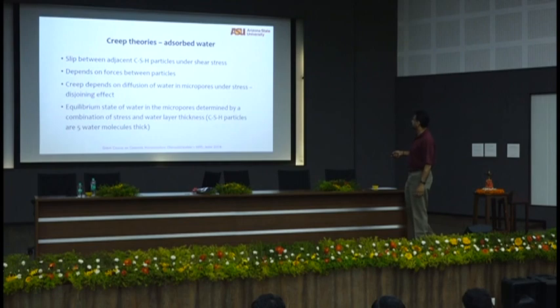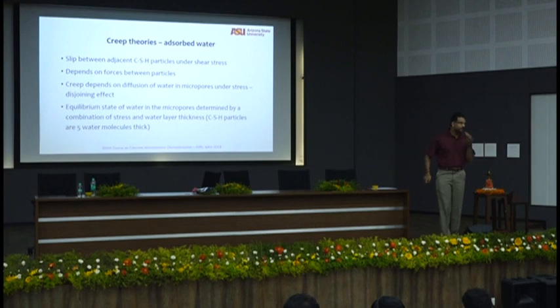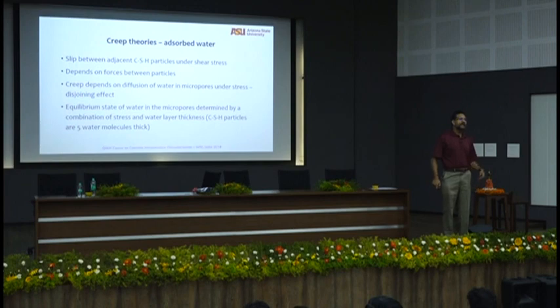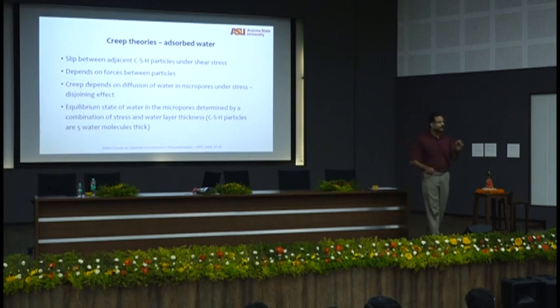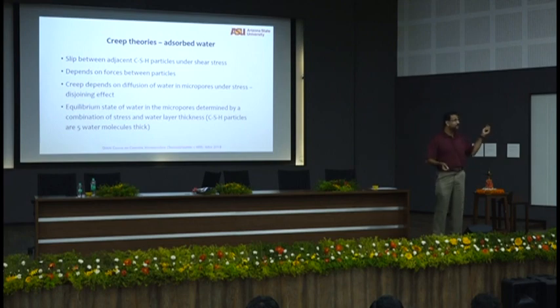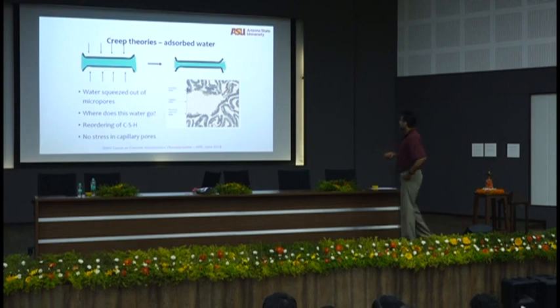Equilibrium state of water is determined by a combination of stress and water layer thickness. CSH particles are roughly 5 to 10 water molecules thick. Basically, which means if you apply enough load to squeeze 5 water molecules out, you have collapsed the CSH layer completely. But that takes a lot of load to squeeze 5 water molecules out. Remember, the stress required is extremely high, because the area of cross section is very low. You are almost doing a point load, so the stress required is almost infinity. Okay, so this is what we talked about.